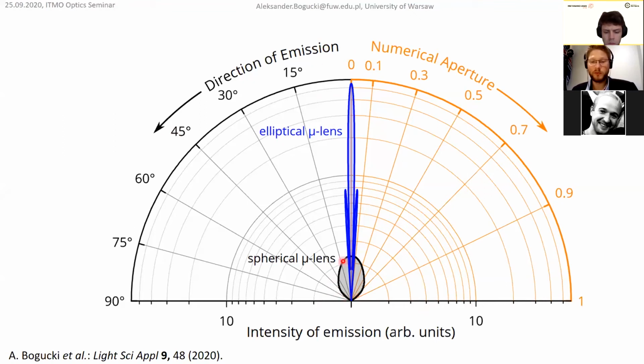And when we compare the blue line, which is the elliptical microlens, to the spherical one, the standard one, you can see this one was pretty equidirectional, so it will emit light in all directions as we expected. This is logarithmic scale, again, I remind you. And the microlens, which has an elliptical shape, results in a very sharp directed emission into a small numerical aperture. So total emission is below 0.1 numerical aperture. So this is very directive emission.